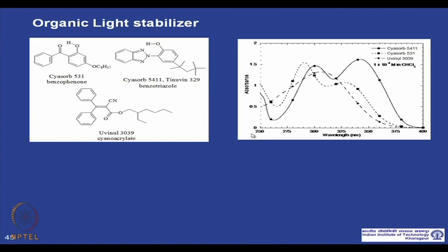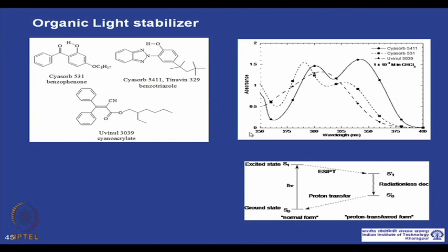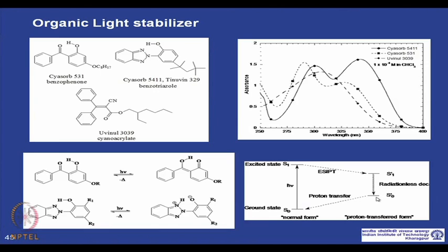Now, the mechanism of this UV absorption is that they absorb, and then at the excited state proton transfer happens, and finally they form a new excited state, from which, by a radiationless process, they come back to the new ground state.